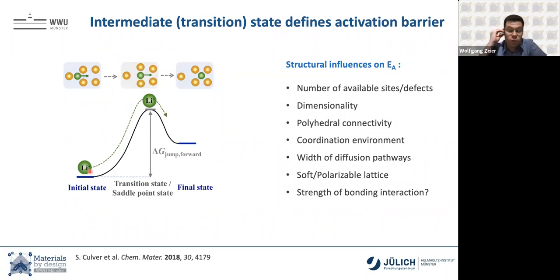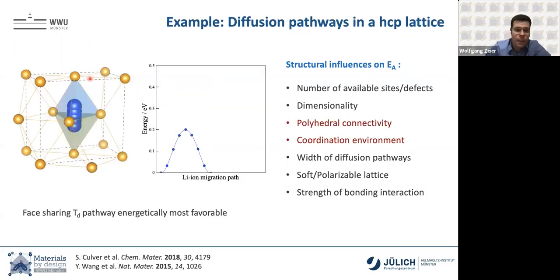And so if you go to textbooks, inorganic chemistry, you'll find a variety of things that are allegedly affecting ionic conductivity. That is the number of available sites. You need space to jump into. If everything is occupied, nothing will be moving. You need a certain polyhedral connectivity. So for instance, if you look at a hexagonally close packed lattice, you have a lithium sitting on a tetrahedron and it wants to jump to the adjacent tetrahedron, it needs to go via this triangular site. This is well connected via a face.